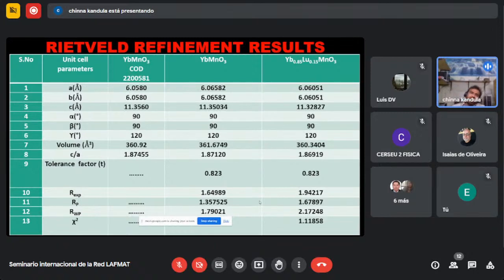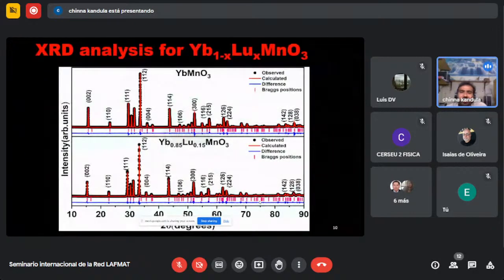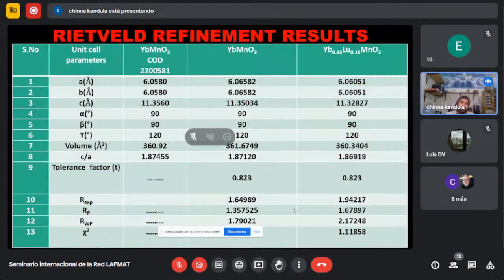Why do I calculate the tolerance factor? And the goodness of fit I will also show here. It comes from the parent compound as 1.7 and 1.1. You can see my plots, showing how good each and every peak fit is. The tolerance factor I calculated here: generally, a perovskite structure like YbMnO3 has a tolerance factor between 0.8 and 1. Generally, for cubic the tolerance factor is 1, but perovskite lies between 0.8 and 1. Our values also lie in that range, so it is a good perovskite structure. This can be visualized in VESTA also. I visualized it, but as of now I am not putting that figure here.